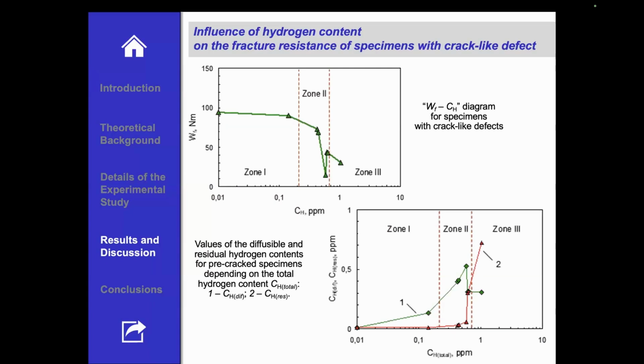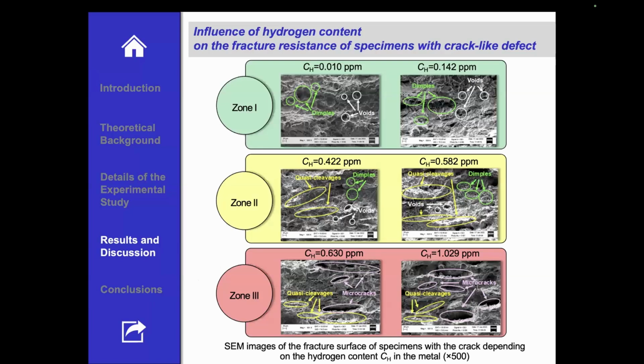A similar investigation procedure was used for the next case, specimens with crack-like defects. Similarly, we see the change of the parameter WF and the next zones. Similarly, we analyzed with the scanning electron microscope. And you see now the first zone characterized by the typical defects of dimple fracture, the transition zone, and the zone characterizing brittle fracture.